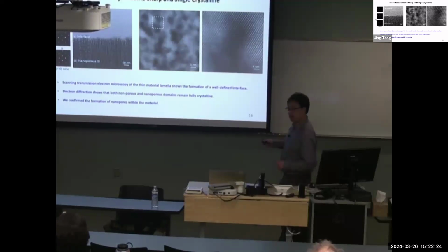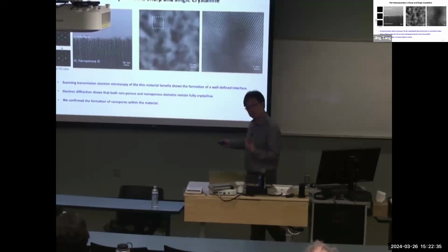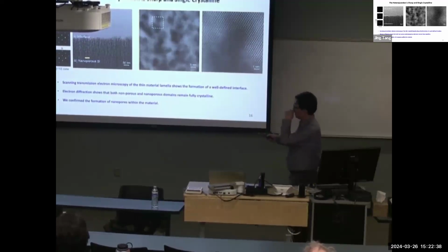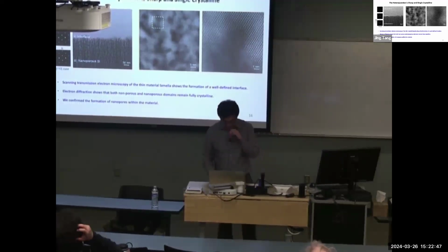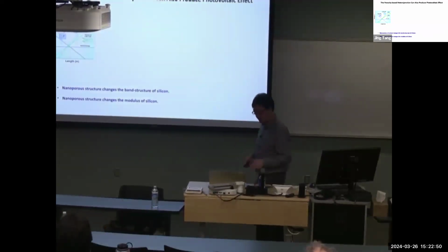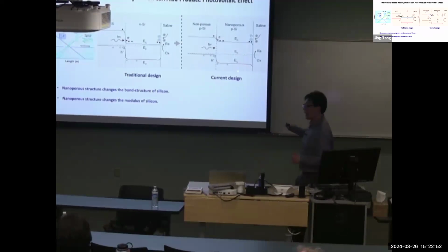These are electron diffraction patterns recorded from 3 different areas: non-porous part, interface, and nanoporous part. What you can see is that those 3 patterns are almost the same, but slightly different, suggesting it's a coherent single crystal throughout the entire material. If you zoom in on this nanoporous region, the feature size or wall thickness is about a couple of nanometers. When silicon becomes this small, the quantum confinement effect kicks in, and you would expect a larger band gap for silicon. Although you start with the same silicon, after etching it becomes a nanoporous structure, and the band structure changes. The Fermi level position with respect to the conduction and valence bands will also change.